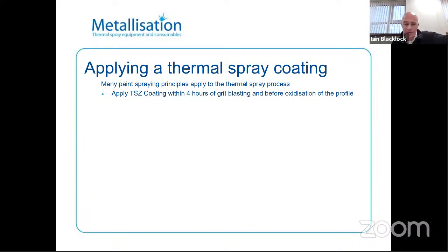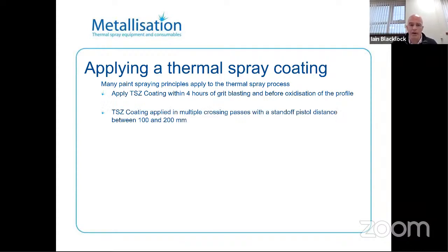Many of the paint spraying principles apply to the thermal spray process. So you apply the coating within 4 hours of grit blasting and before oxidization of the profile. Any oxidization of the blast profile can affect the adhesion of the coating, in the same way with paint coatings. Thermal spray zinc coating is applied in multiple crossing passes with a standoff pistol distance between 100 and 200 millimeters. It's one of the key aspects of metal spraying and thermal spray is the spray distance, because the further away you get, the cooler the particles are and the less adhesion you get and the more dust you generate if you're not doing it correctly.